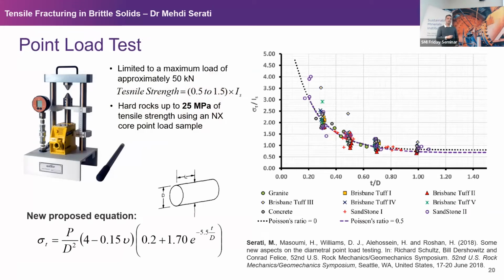We also tried to challenge our 3D theoretical framework to understand the point load test. You don't need me to tell you, you experts know better than me that the point load test is an index test. One way to do it, you have a cylindrical sample, you apply concentrated load using these conical contact points, and generally speaking, you get an estimate for UCS, but also we have an empirical equation that you can use to get an estimate for tensile strength. Using the theoretical framework, we propose this expression. It's purely mathematical, it's not experimental.